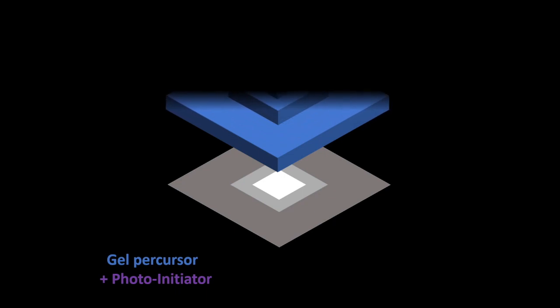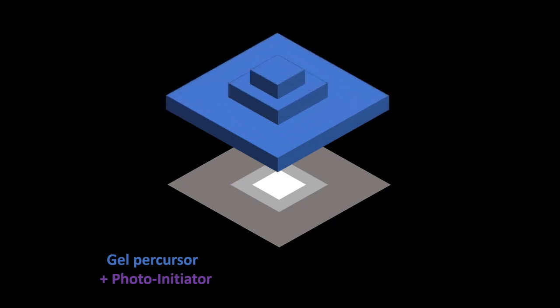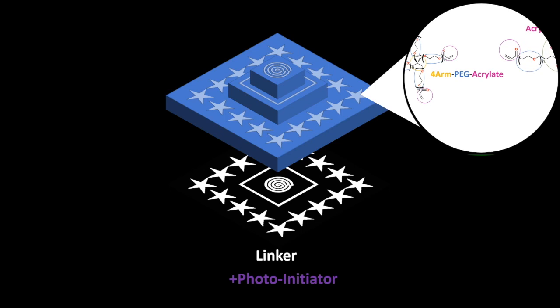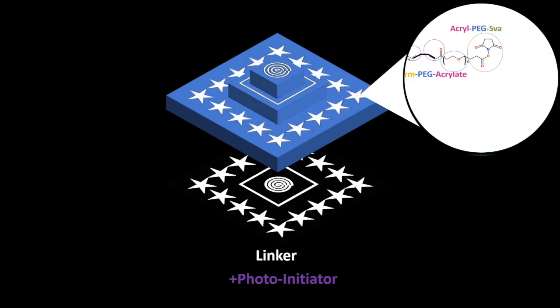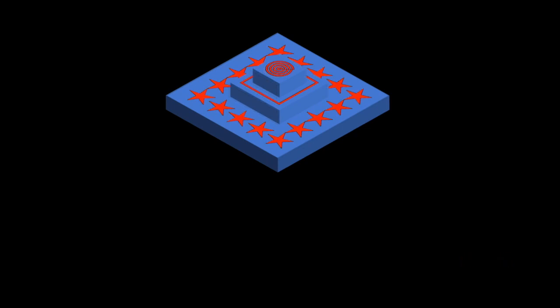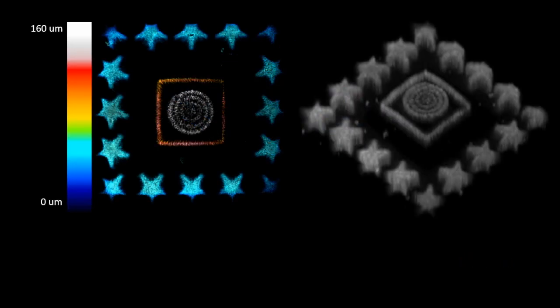After the structuration step, we can graft patterns of photolinker aligned onto the topography. The photolinker serves as an intermediate. It will subsequently react with polylysine to form a protein-friendly layer onto the hydrogel. Indeed, proteins of interest can be spontaneously adsorbed to the PLL. This successive structuration and decoration generates hydrogels with heterogeneous topographical and chemical features.